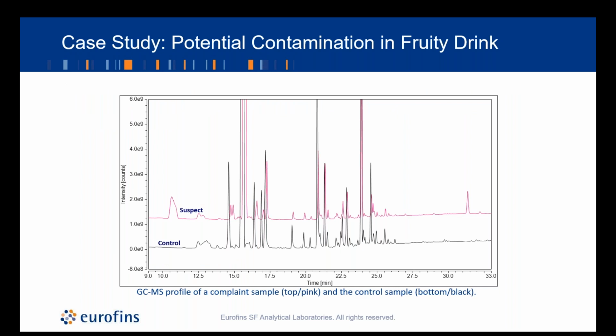Once again, we have our suspect chromatogram on the top in red, and on the bottom we have our control in black. You can see these profiles are more complex than what we saw for our cookie samples, and this is also a zoomed-in view so that you can see some of the minor peaks here in addition to the much larger components. I'm going to highlight several compounds we picked out that we thought would be of interest, and these are isopropyl alcohol, 4,1-methylpropylphenol, and 2,4-dichlorophenol.